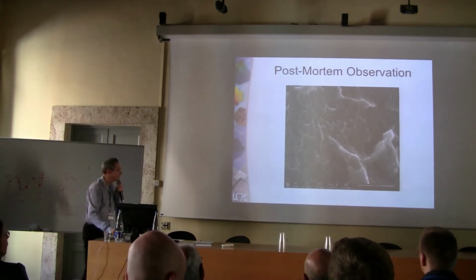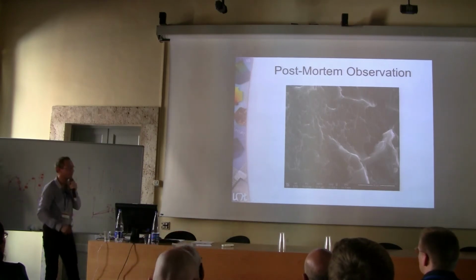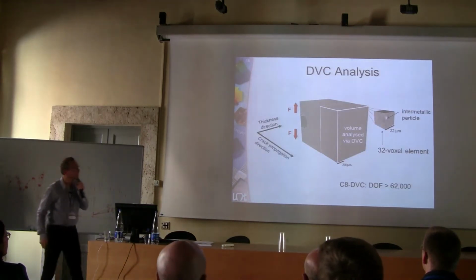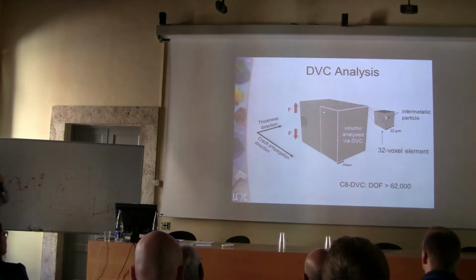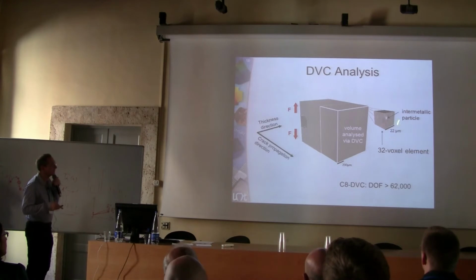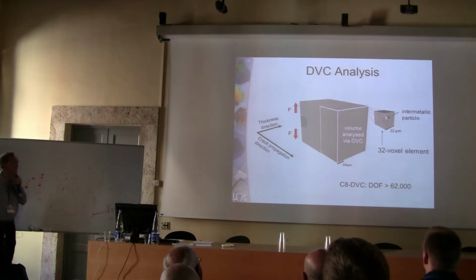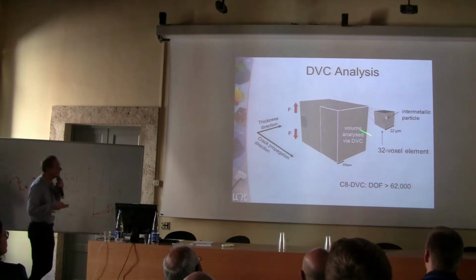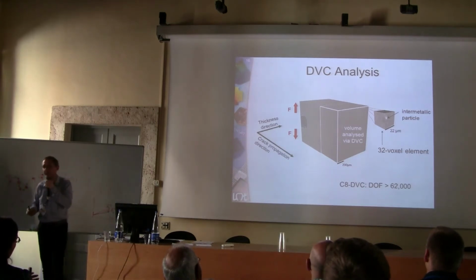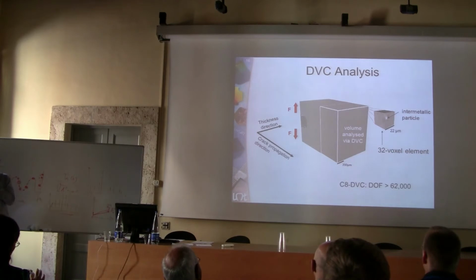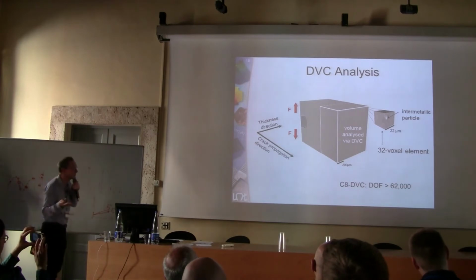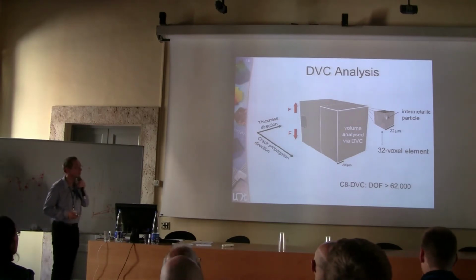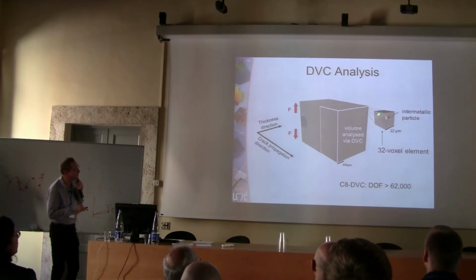Now, the problem is that this is post-mortem - what's happening during the experiment? To understand that, what was done was to image a volume close to the notch root, and then analyze this volume with digital volume correlation. In this first example, we used regular hexahedra, a finite element mesh, meaning our unknowns are now the nodal displacements associated with the discretization. Here is an example of one of these elements.